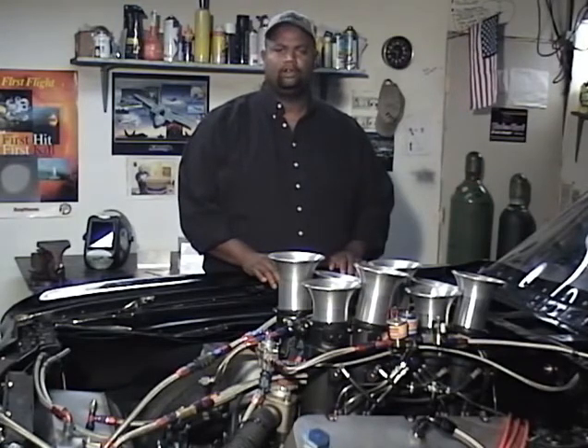Take the time to get a clean carbide burr and carve out that inclusion, or as the people in X-ray call it, an MDI, a more dense inclusion, tungsten being more dense, so it shows up bright white on an X-ray. You will not hide it, they will see it. So make sure you get it out of there and replace that with clean weld metal.